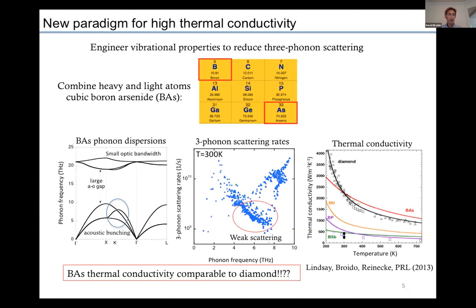And it turns out that there are features in the phonon dispersions of boron arsenide, which are shown in the left plot. There's a collection of such features that conspire to give very weak 3 phonon scattering rates for a frequency region circled in the center plot. And that means that those phonons in that frequency region can carry a lot of heat, and our predicted thermal conductivity for boron arsenide that we published 7 years ago or so was comparable to that of diamond. So this was a quite surprising and exciting result.